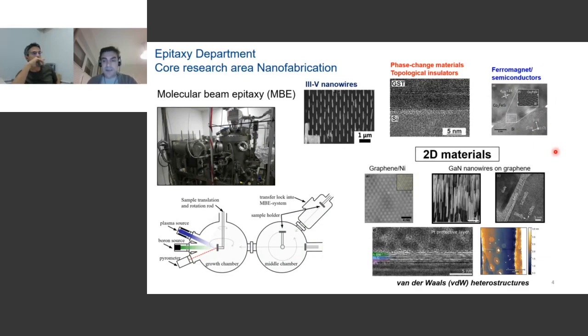That is an activity that we started there in 2010. And we've been dealing with different types of systems, not only growing a 2D material like graphene on substrates like nickel. Here I show you an STM image of a graphene monolayer on nickel, where you can see this nice moiré pattern coming from graphene. But we also have been preparing hybrid structures with very sharp interfaces. Here I give you an example of gallium nitride nanowires that have been grown on MLG. Here MLG means multilayer graphene, and you can see again the clear interfaces that are possible when you grow at very precise and clean conditions like in MBE.